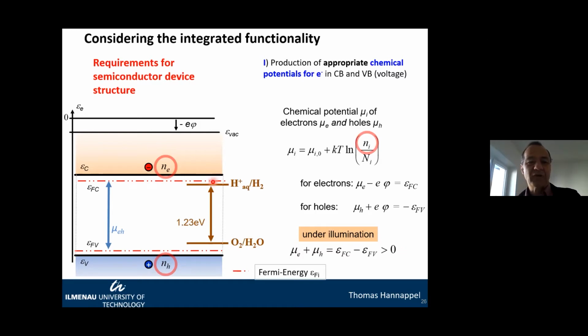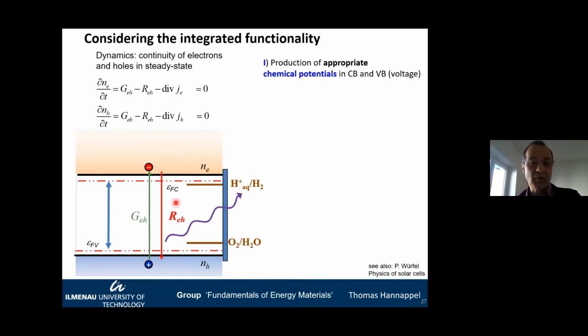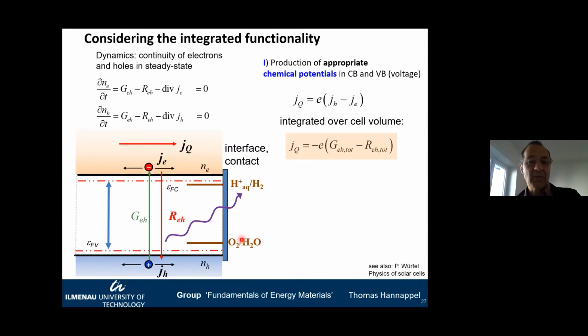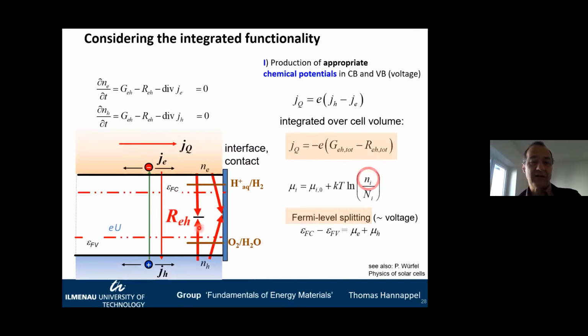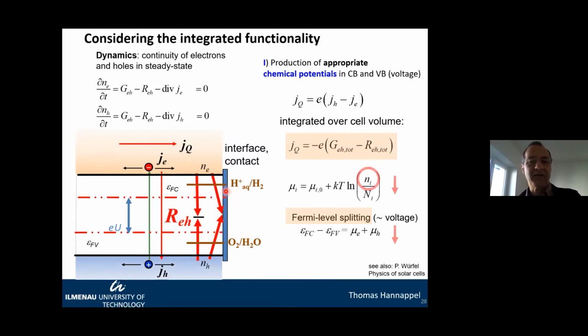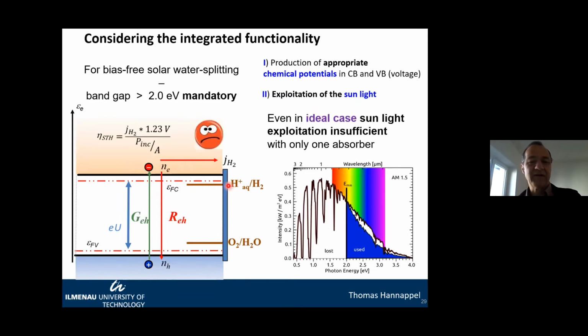And if we then compare this to the redox potentials of water, here you can see of hydrogen and oxygen, you can see that we need 1.23 electron volts, and then it can be reduced, even the voltage, by recombination processes in the material and at the interfaces here, and this all degrades this voltage which we need. Finally, even in the best case, if we just use one absorber, we can only absorb a small portion of the solar spectrum, even if we do the best of everything. So how to deal with it, how to improve this? And this is the question which I raised.